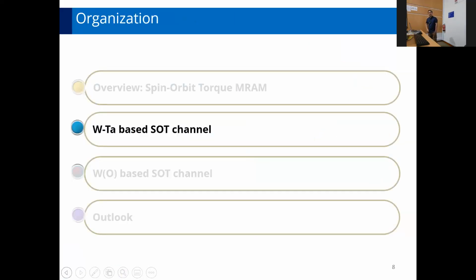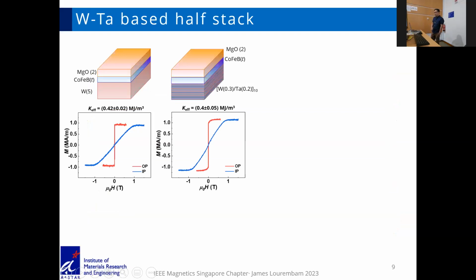So with that overview, I'll go to the first part, which is using a tungsten-tantalum based SOT channel. What we did in this: typically a magnetic tunnel junction has the free layer and the reference layer part. The free layer typically has 3 components. One could be tantalum or tungsten as the channel, which could also act as a boron getter. Then you have the cobalt iron boron, and then MgO.